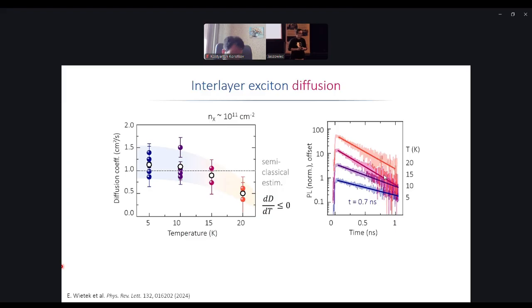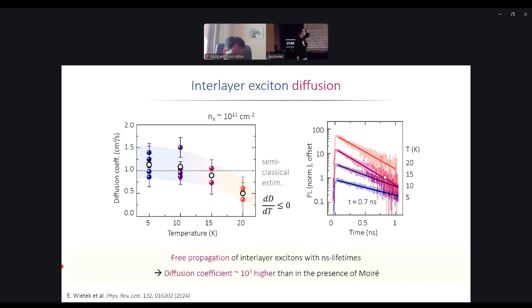They're still there. Which means that in many cases, when you go from single layer to a bilayer, and you observe your lifetime changing from hundreds of picoseconds to hundreds of nanoseconds or even microseconds, it's quite likely, I would not claim that this is every time the case, but it's quite likely that this is a combination of reduced radiative coupling and also localization. Now you get rid of localization, you make the potential flat, you make the exciton move, and what one recovers here is more or less monolayer physics. Okay? So again, if the diffusion coefficients are high, the lifetime can be short, because the excitons are reaching non-radiative centers faster, and this is one of the results here.